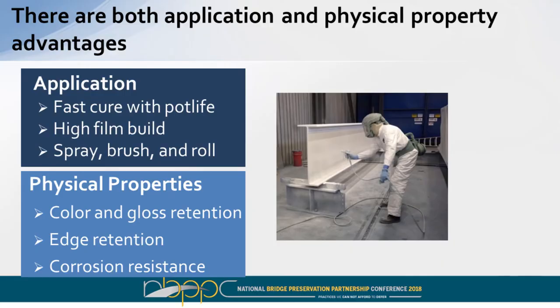On the physical property side, these materials, the polyaspartics, have very similar color and gloss retention as traditional industrial maintenance grade polyurethanes, those that you would find being used on steel bridges today. However, they have excellent edge retention, in many cases greater than that of a traditional polyurethane. So what that does is you're getting more film thickness on the edge, where you're going to see corrosion breakdown first. And from the corrosion resistance standpoint, these types of products can be used in direct-to-metal applications more for moderately corrosive environments, and can also be applied over zinc-rich primers for more of that heavy-duty protection, which you might need on a steel bridge.